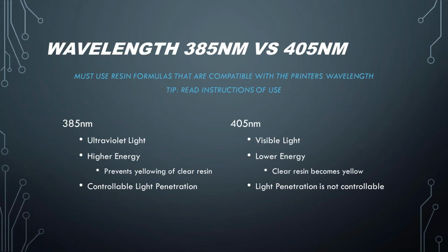So let's cover the differences in wavelength between 385 nanometers and 405 nanometers. Right off the bat, you must use a resin formula that is compatible with the printer's wavelength. If you have a 385 nanometer resin, you cannot use that in a 405 nanometer printer without having some sort of accuracy issue. If I was to use a 385 nanometer resin in a 405 nanometer spectrum printer, you'll actually have resin that is cured in areas that you didn't want it to, because the light penetration is actually higher in the 405 nanometer. So just a tip, read the instructions of use for any resin. I can't stress that enough. It is crucial that you read that.